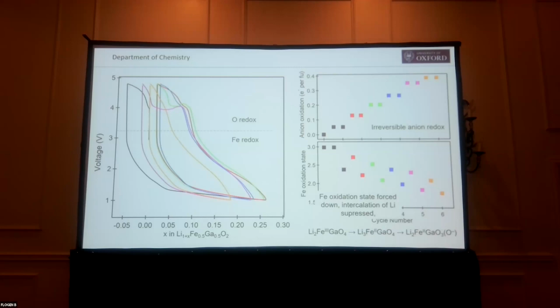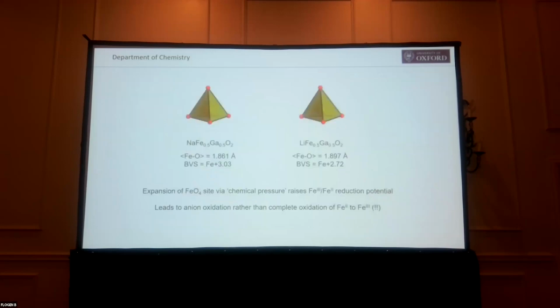One thing that is surprising is that we get anion redox competing with iron 2 to iron 3, not iron 3 to iron 4. That seems generally strange. So what's going on there? Well, we think this is a feature of the chemical pressure I mentioned before. If we take the sodium, iron, gallium material, where the iron and gallium are ordered, we can look at the local coordination of iron.